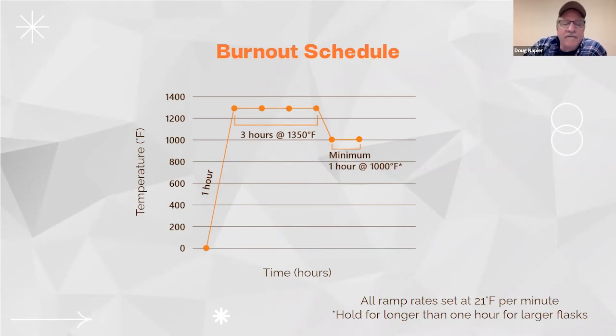These numbers might vary. If you're using bigger flasks, you might want to let it stabilize a little bit longer. But this is what I usually use, and it works well. A lot of people say that you get up to 700 degrees, or you let it sit at 300 degrees so that it dries out, and then you get it up to 700 degrees so that the resin gets out of there a little bit better. I don't know the science behind it. I just know that this works for me, and I get pretty good results this way.